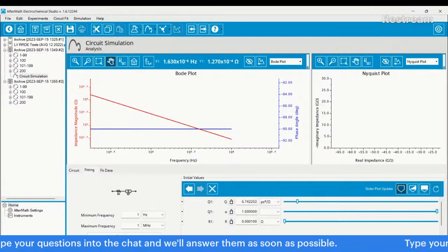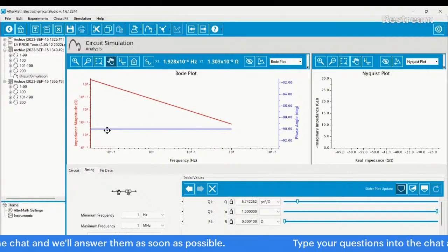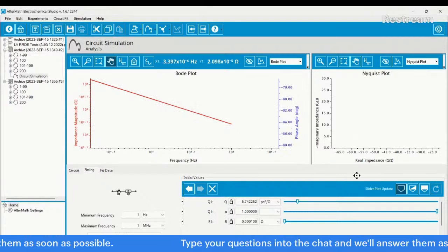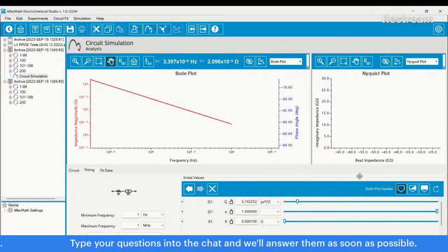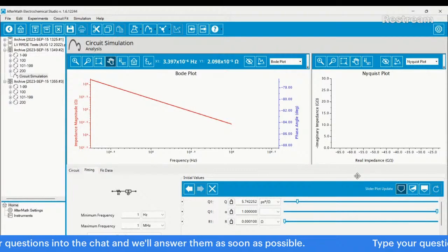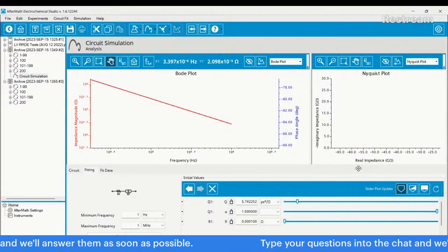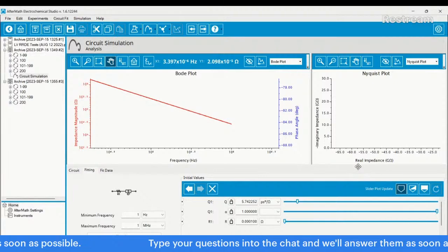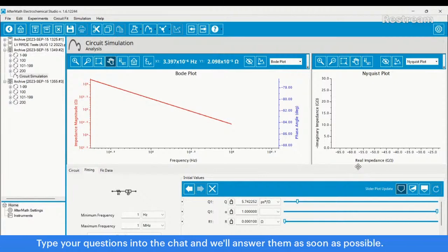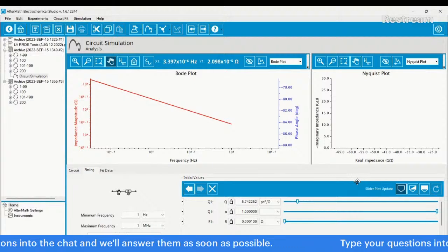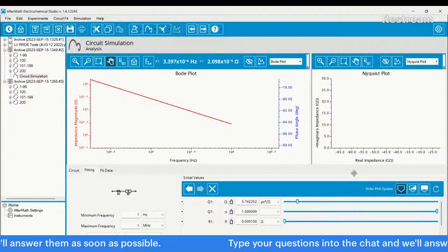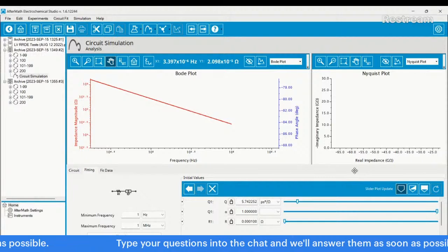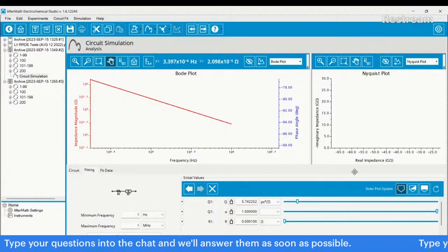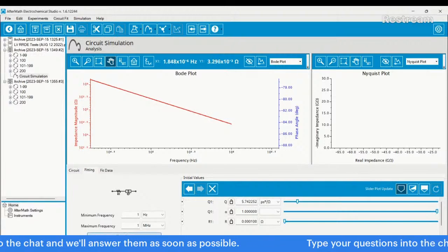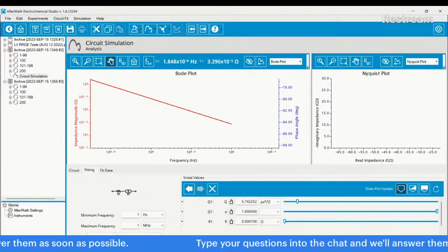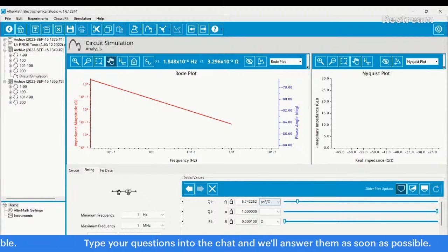And he also wants to know what the current thickness of our silver chloride reference electrodes' glass is. I think it's about 2 millimeters. It's not the same everywhere because it changes at the bottom where it curves. There's a taper when you do the glass that way. I think it's 2 to 3 millimeters thick, something like that. In fact, after learning about this phenomenon, I calculated the capacitance based on a rough amount of depth, and I came up with like 8 picofarads, right where it's supposed to be.